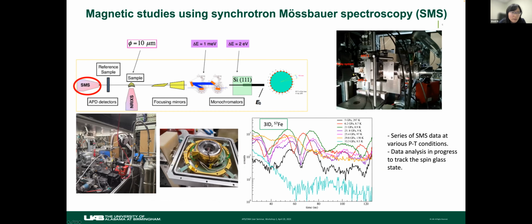Okay, so to understand the suppression of magnetism in iron tin at room temperature, we want to know whether the magnetic order temperature is just decreased by applying pressure to drop below room temperature, or whether the magnetic moment is completely suppressed. So to understand this point, we loaded a sample, put it in a cryostat, cooled down, and took Mössbauer data at different temperatures and pressures.